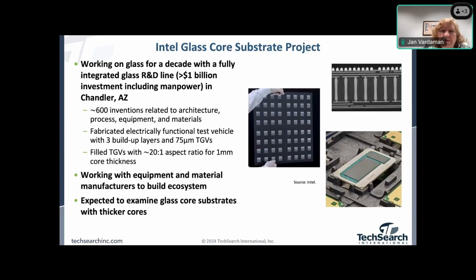Intel has been working on glass core work for about at least a decade, with a fully integrated R&D line, about $1 billion in investment, including the manpower in Chandler, Arizona. They have like 600 inventions related to architecture, process equipment, and materials. They did some fabrication of an electrically functional test vehicle with 3 buildup layers, 75 micron TGVs, filled TGVs with a 20-to-1 aspect ratio for like a 1 millimeter core thickness.